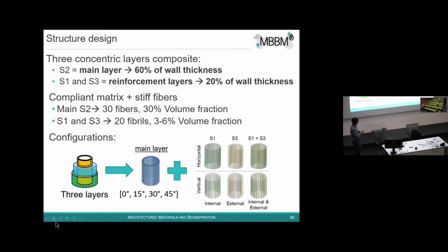So we had the main layer with fibers at angles from 0 degrees vertical up to 45 degrees. And as reinforcing layer, we consider both only horizontal and vertical fibers. So we try to reduce the parameter space a little bit and to see the interplay in terms of mechanical properties when we play with these structures.